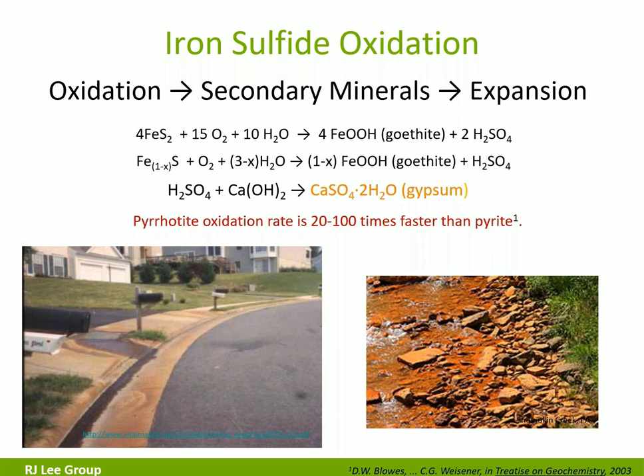Related to aggregate production, access to air, the first sign that you have a problem is that you'll have rusted stockpiles. So again, access to air is number one. And what we found is that material above the water table may have had some weathering already done, where the reaction had taken place previously, so you don't have the severe staining. But once you get below the water table, the rock hasn't seen air before, and that rust and oxidation really takes off pretty quickly.